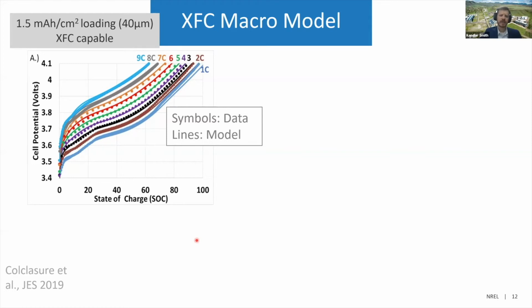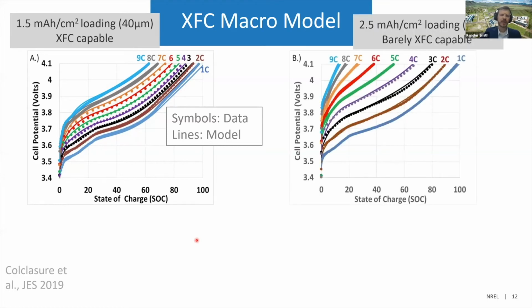So we've got multiple different loadings of cells that Argonne has built. If you have very thin electrodes or a low loading, 1.5 milliamp hours per centimeter squared, this type of cell is very extreme fast charge capable. You can see we're going up to a 10-minute charge, 6C rate, with no problem here. Whereas as you go to a higher loading, and this would be a cell that is perhaps around 180 watt hours per kilogram, so decent energy density, you can only charge at a 10-minute rate, 6C rate, up to about 35% state of charge before you hit a cutoff voltage.